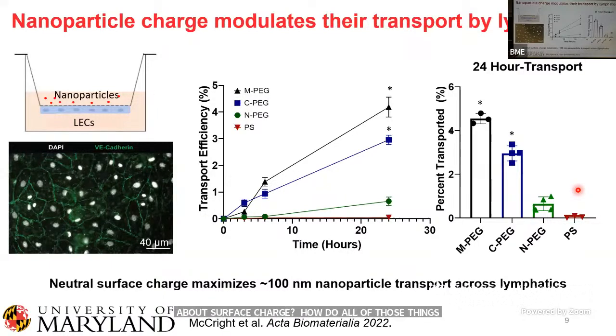But here, you're trying to get to the lymph nodes, you're trying to get into the vessel. So we've got our lymphatic endothelial cell monolayer on the bottom here, and then we can put our nanoparticles or other materials of interest on top and actually just sample on the bottom over time to try to understand how are they transported across. So we can confirm we've got a nice monolayer, so we're not just getting transport across because there's gaps between the cells. This is actually paracellular and transcellular transport that's happening.